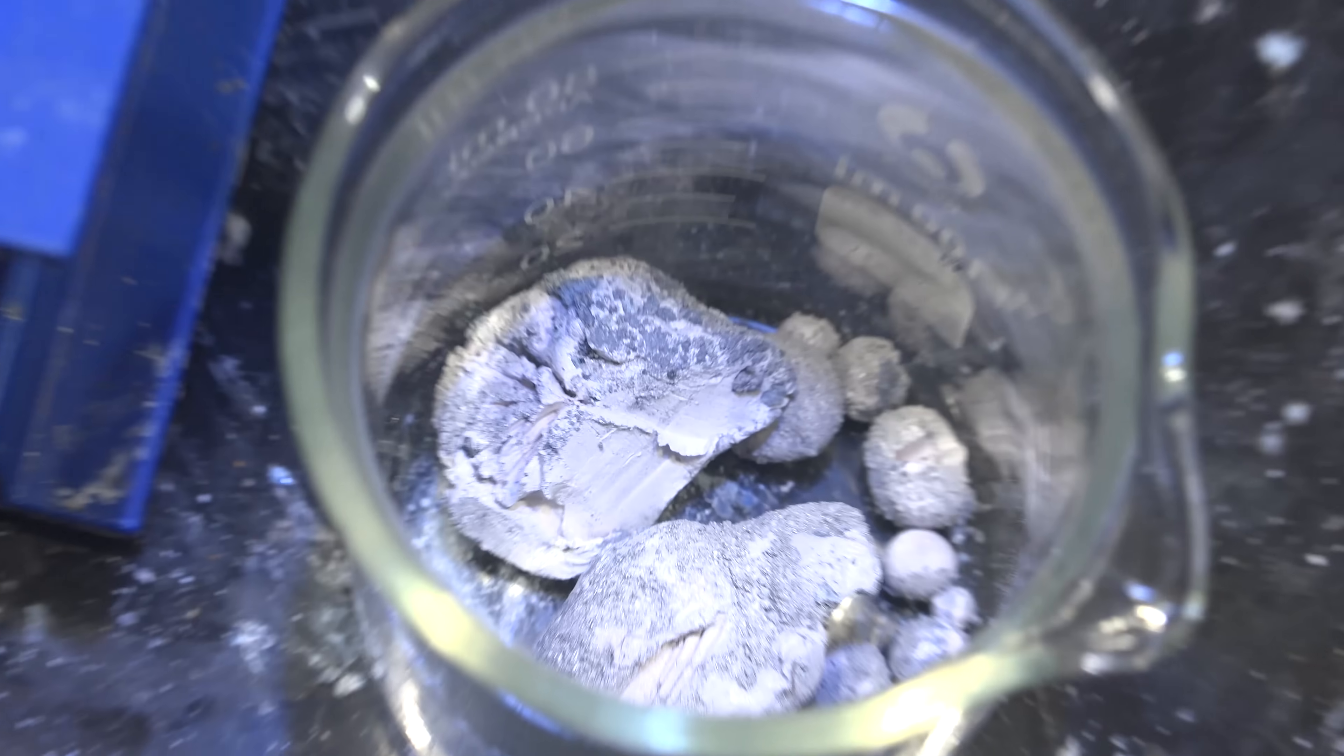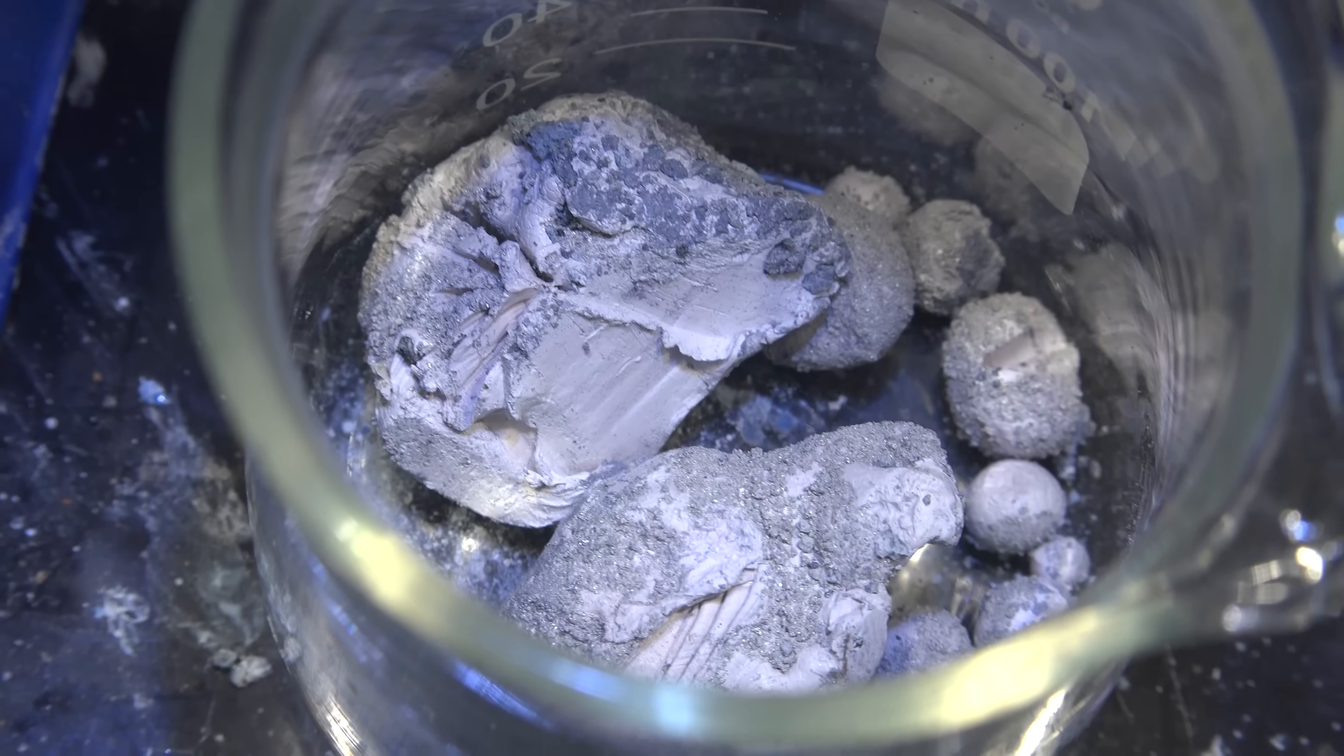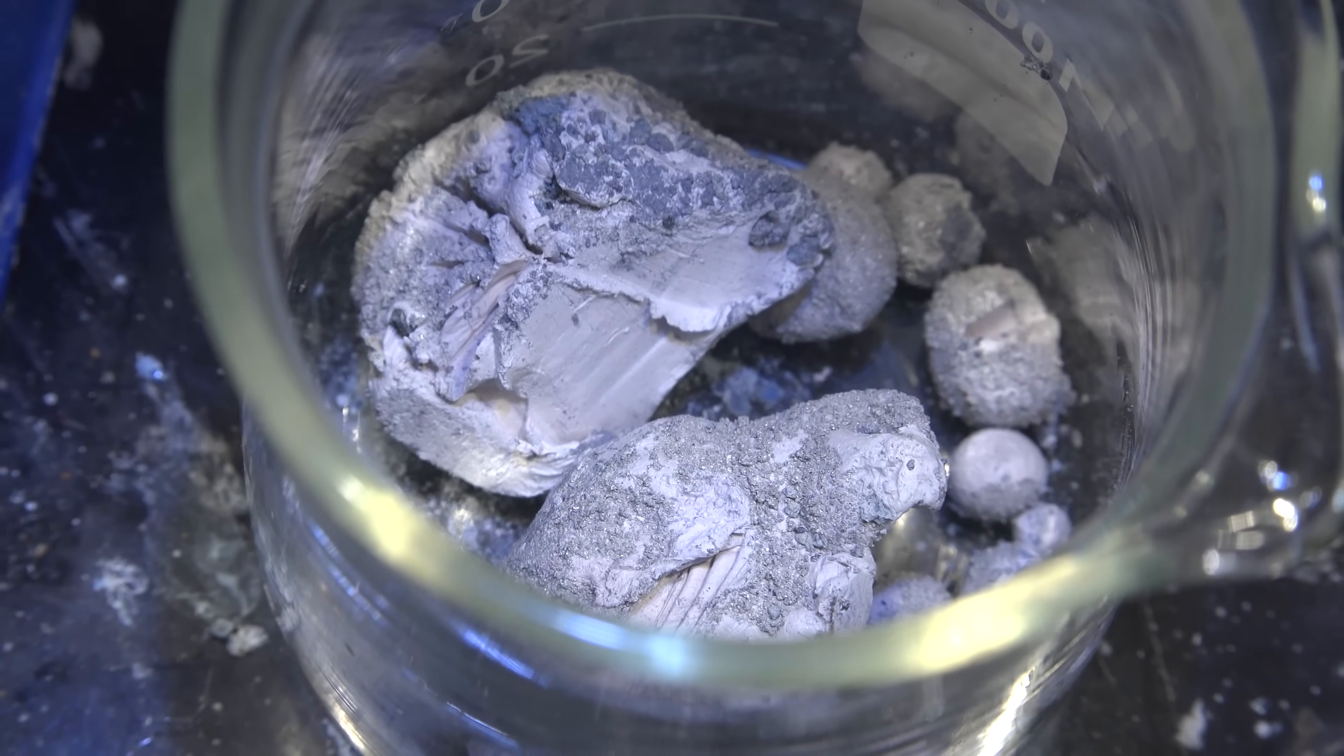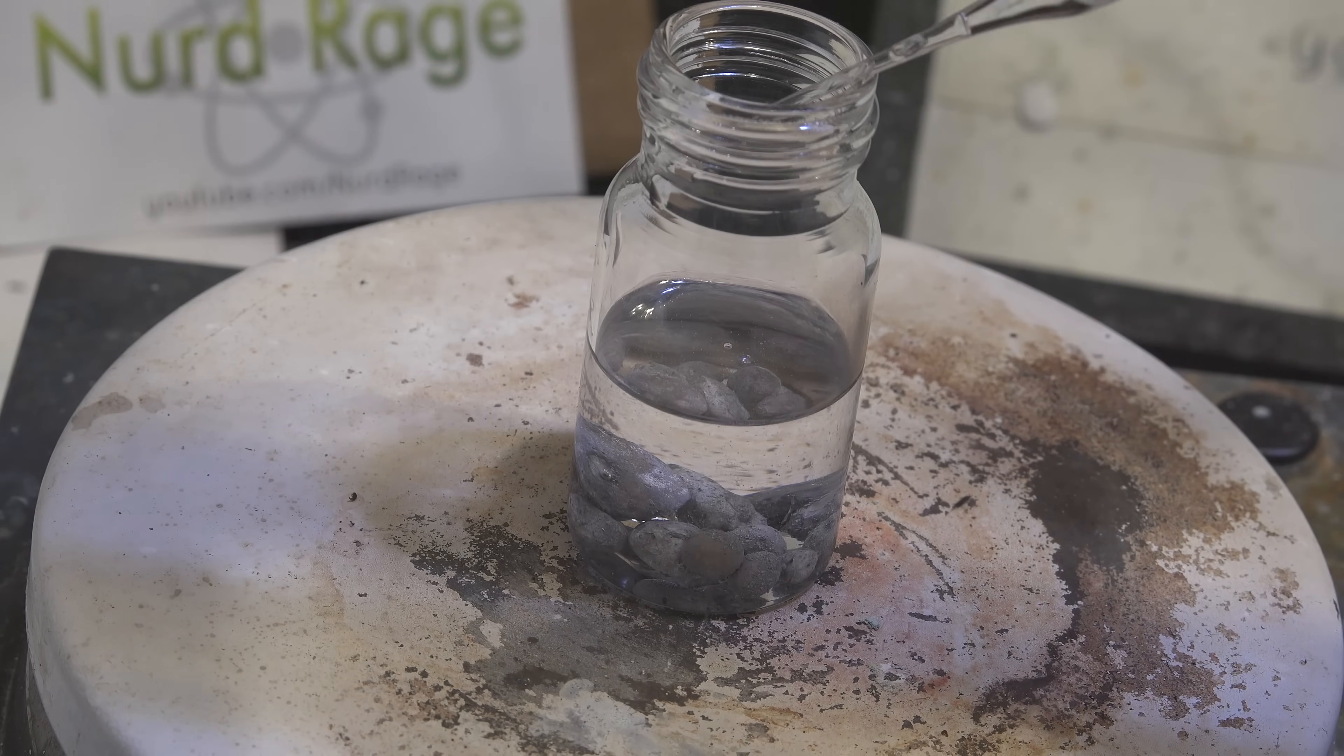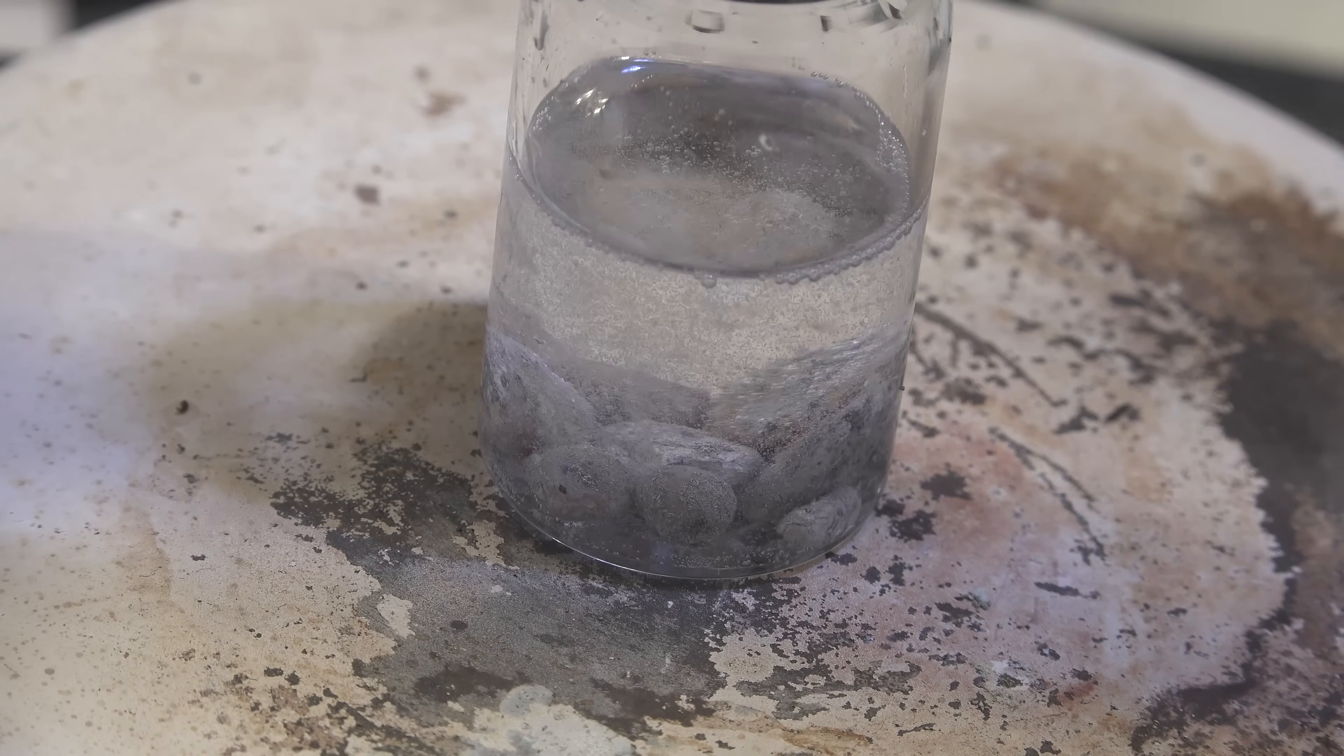Okay now back to the sodium. Now there are still bits of magnesium oxide slag sticking to them and some of the spheres are rather small. We can remove the slag as well as coalesce these smaller pieces although it's not strictly necessary for most purposes like solvent drying. Anyway to clean and coalesce them, get some in a vial or a beaker and cover them in mineral oil. Then add in a small amount of isopropyl alcohol. A few drops to start. Now heat up the mixture until the sodium melts.